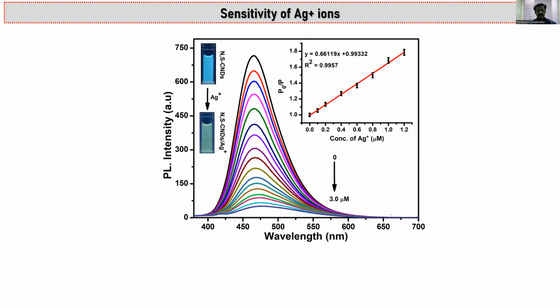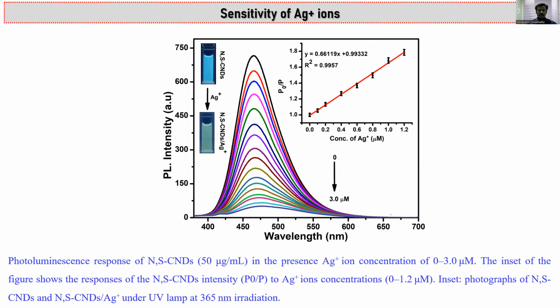This one is the sensitivity of silver ions. We can confirm this from photoluminescence quantitative detection. In the inset figure we can see blue emission, and then on adding the silver ions we get a faint green emission. This shows the photoluminescence intensities in the absence of silver, and with different concentrations from 0 to 3 micromolar. You can get 90% quenching from the carbon dots. We can confirm from the studies the Stern-Volmer plot using the absence and presence of intensities, with a linear fit of 0.99. So this complexation we can get with 1:1 stoichiometry.